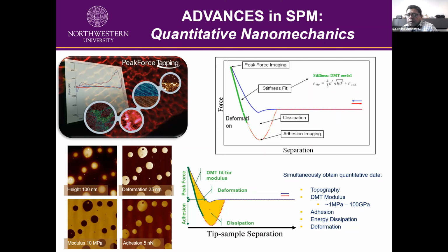And we have that capability in the Bruker BioScope Resolve, and we can do both in air and liquid. And the important thing about this technique is that you do your calibration first before you measure the unknown sample. This is pretty standard in an indenter system, where you calibrate on a known sample, and then you can measure the hardness of unknown materials.